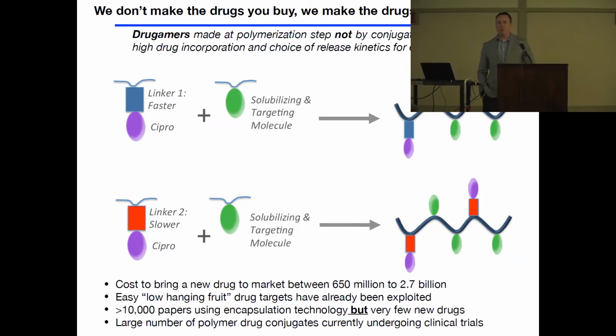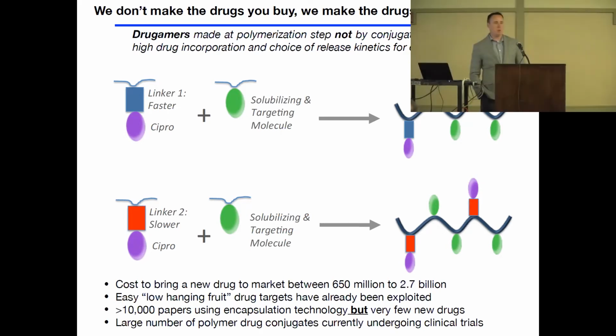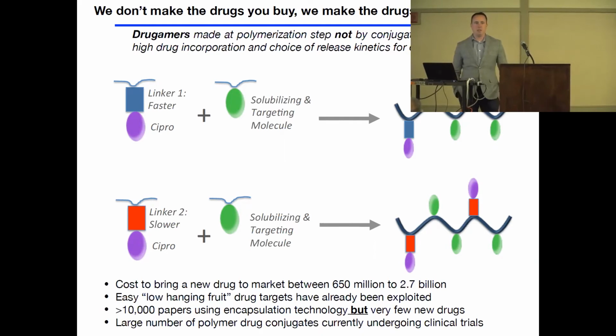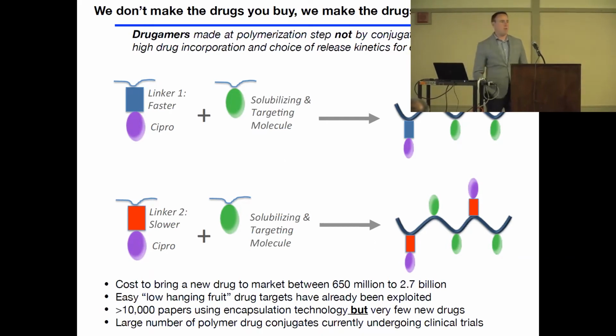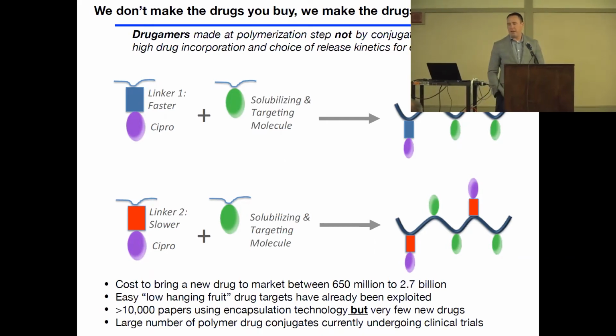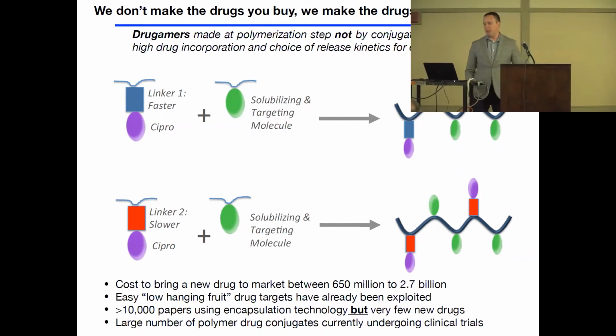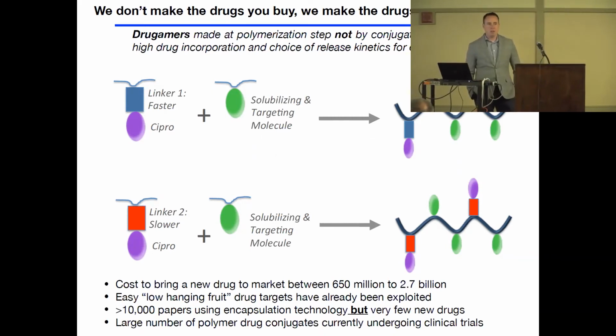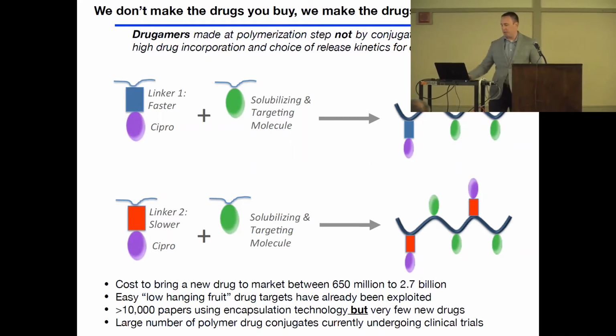To get around this, we've developed what we're calling drugamers. So we attach pretty much any drug you want to a polymerizable group via a degradable linkage, and we can control this linkage. All the synthesis can be done in GMP laboratories, giving you a pharmaceutically pure compound. And then in a single step, we polymerize it all together with targeting moieties and molecules to solubilize everything.